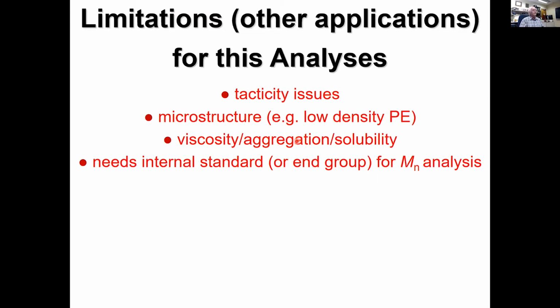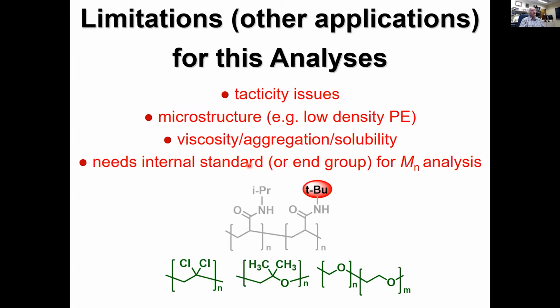You also have issues of viscosity, solubility, or aggregation. I'd point out one example: we've done a lot of work with N-isopropyl acrylamide, and we've made copolymers with isopropyl and tert-butyl groups. When we try to analyze these, the problem happens in NMR spectroscopy. These materials, because they have a tert-butyl group, tend to aggregate. They have a so-called lower critical solution temperature—they fall out of solution as you heat them up.